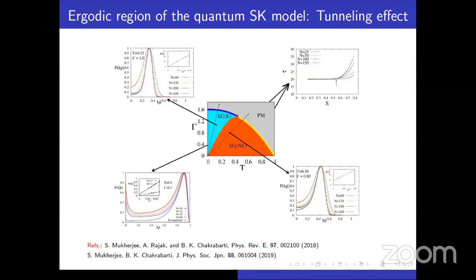S is a measure from the quantum expansion line towards the higher temperature. If you are in the blue region, it says that I have decreased the temperature and gamma along this line, from para to the singlet. If we do that, to get the singlet ground state, the time required is not dependent on the system size. This is a signal of an ergodic-like system.